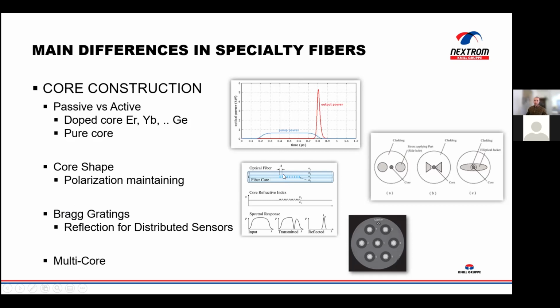You have Bragg grating, where you have slight deformation in the core to create a reflection at certain points, and then you can measure the spectral response for the transmitted and reflected. By observing any change in this reflection, you can measure what's happening in the fiber, whether it be bending or stretching. So that's mainly used for structural stress sensing. Multi-core fiber, so you can actually combine many different types of fibers into a single fiber, so you can be measuring temperature, pressure, stress, all at the same time.